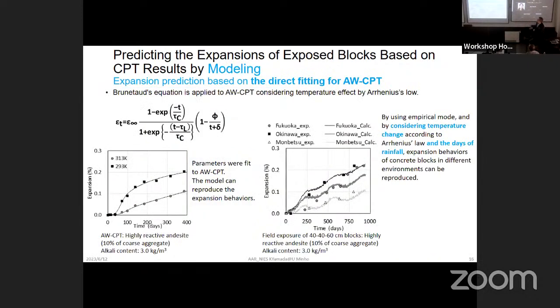And there is another way of modeling. We have this kind of expansion test at different temperature. And this expansion behavior can be reproduced by this kind of equation. By fitting this equation to this test result, we can get some parameters. Then this model was applied to the field expansion result. Then, as you can see, there's a good coincidence.